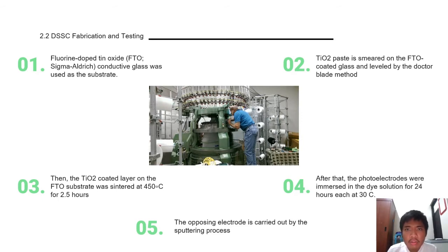The electrolyte solution was synthesized by mixing 3.3 grams of sodium iodide at 99.95%, 523.875 milligrams of pure iodine at 99.95%, 5.481 grams of heteropolyacid or HPA, and 30 ml of acetonitrile.